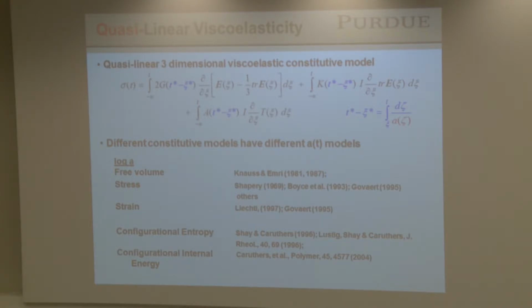Now, what we've done, and my group has participated in this piece, is say temperature isn't the only thing that can affect deformation or the material response. In other words, if I pump energy into the material by mechanical work, that will affect the rate of relaxation as well. So we took this general three-dimensional model that we have here. Notice this is the shape-changing part, and that is the bulk part. Notice the relaxation now is occurring on this material time scale. And there's a third term, which is a thermal stress part, and it says how much stress comes when you increase the temperature but hold the volume constant. So this is a thermodynamically consistent way of modeling the process.